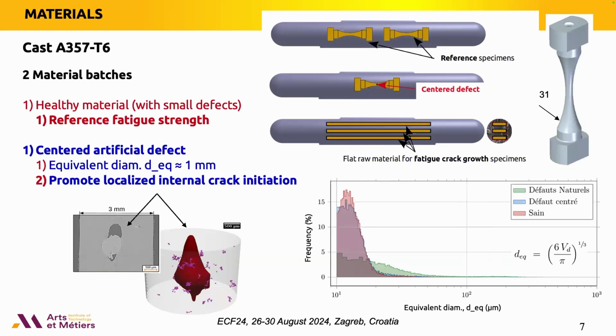So we have created artificial internal defects with a diameter of a little bit less than 1 millimeter, around 700 or 800 micrometers. So these big defects that you can see here, on the left, you can see a slice of the tomography, and you can see in a specimen with a diameter of 3 millimeters, the internal artificial defect, which is produced by a small piece of salt.